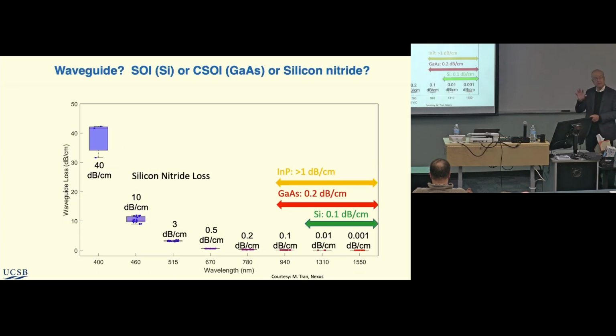So everything's now silicon photonics, but silicon photonics with silicon waveguides. We do a lot of work on other materials, either compound semiconductors on insulator or silicon nitride. The advantage of silicon nitride is that the losses are a tenth dB per centimeter, so much less than silicon, much less than gallium arsenide or indium phosphide. That allows us to make higher Q resonators, which allows us to make better lasers, lower noise lasers in particular, and also lets us work into the visible.